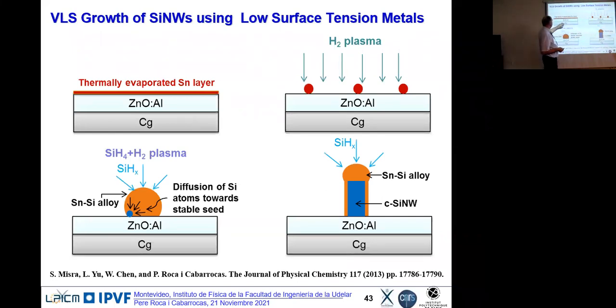drops. So we have the glass, zinc oxide, a thin layer of tin evaporated, then with a hydrogen plasma, you can reduce this thin layer to make it into drops, liquid at 230 degrees. Then you switch from hydrogen to silane hydrogen, you start to produce radicals, which are absorbed in the metal tin. And from that, you are going to grow vertical crystalline silicon nanowires. That's called the vapor-liquid-solid process.